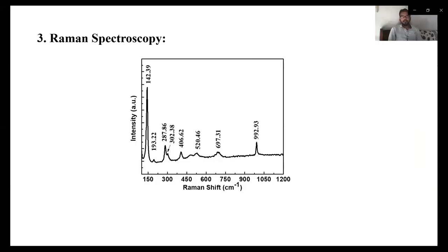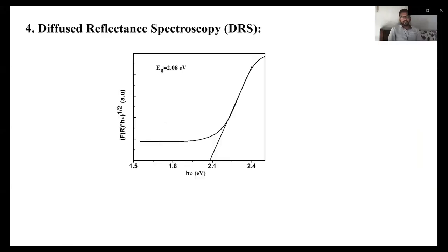This is Raman spectroscopy. The Raman spectra of the prepared material is well matched with the reported research paper. Raman peaks arising at different Raman shifts, such as 287.86, 406.62, and 992.93, are signature peaks of the prepared material. And this confirms the orthorhombic crystal structure of the prepared material.